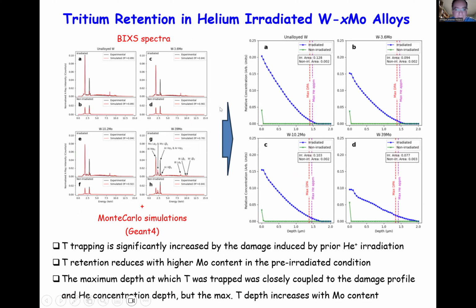Nearly done. So you can look at the spectrum, and then from there, after some simulations, you can get the tritium profile with or without pre-implantation. You can compare with the damage or the helium profiles. So tritium trapping is increased by the damage. So if you have helium implantation prior to that, then you retain more tritium. That's bad news. Tritium retention reduces with a higher amount of molybdenum content, so you can tweak the chemistry of the material and minimize or reduce the amount of tritium retained. But the maximum depth at which the tritium is trapped increases when you increase the amount of